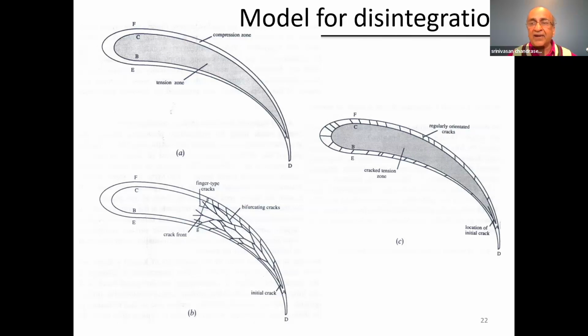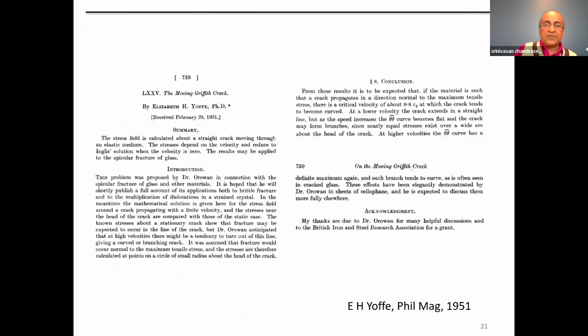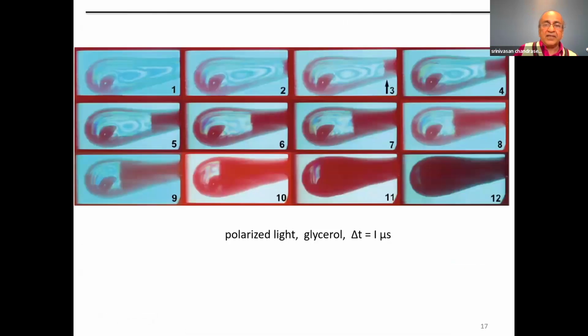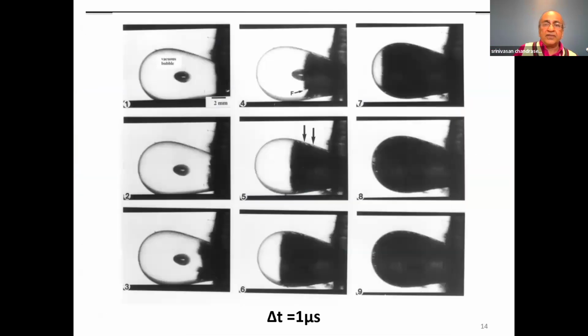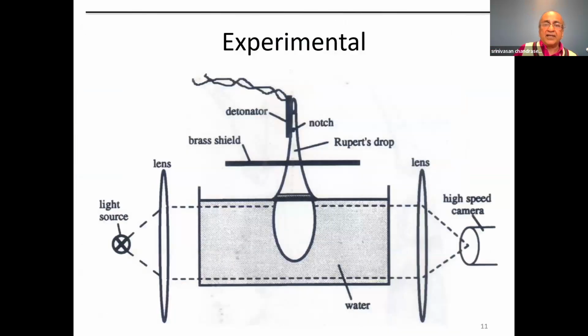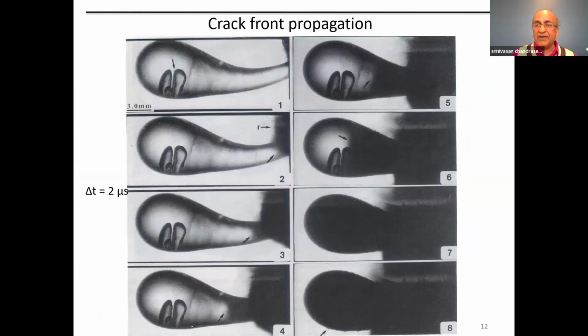So is that clear? And then eventually this bifurcation goes all the way from the tail to the front, and then the entire core is made of fragments. And in figure C, you see that shown as a dark region which encompasses the core of the drop. So this is why the interior of the drop is completely dark when the bifurcation happens.